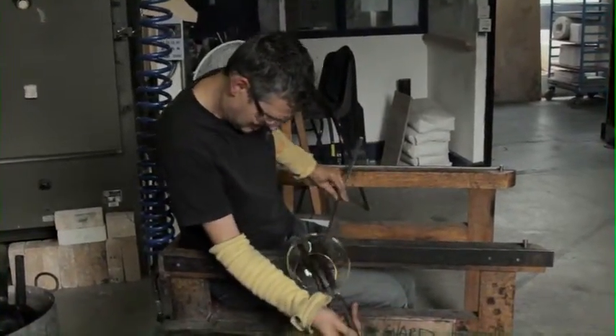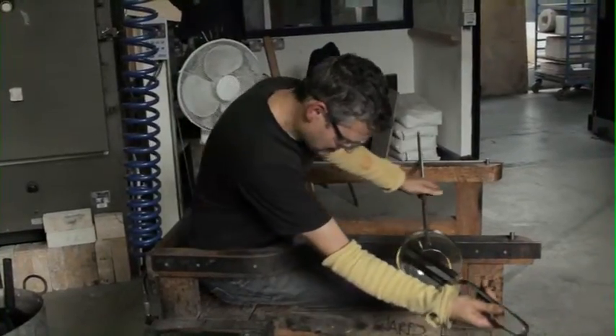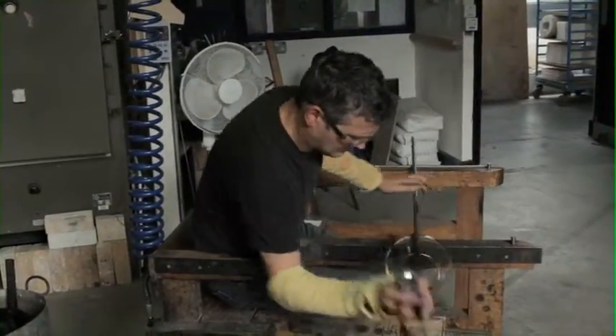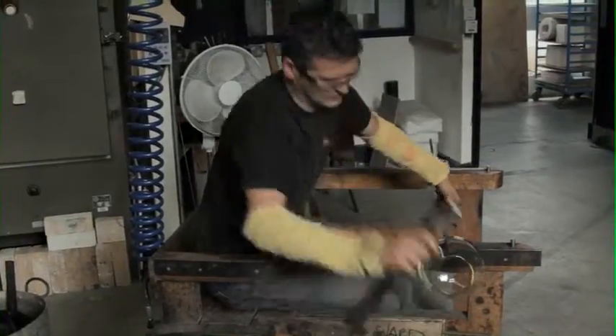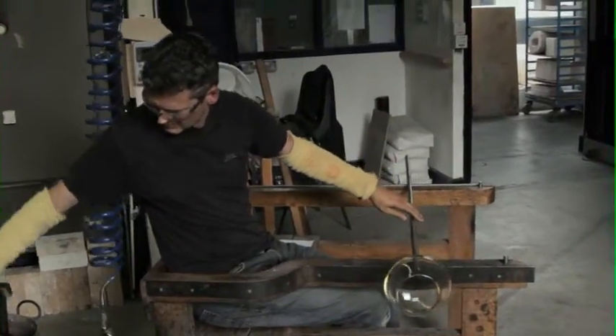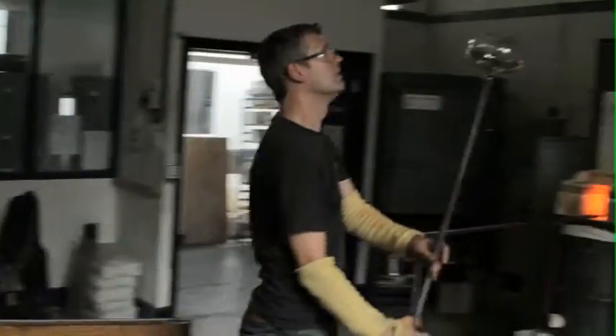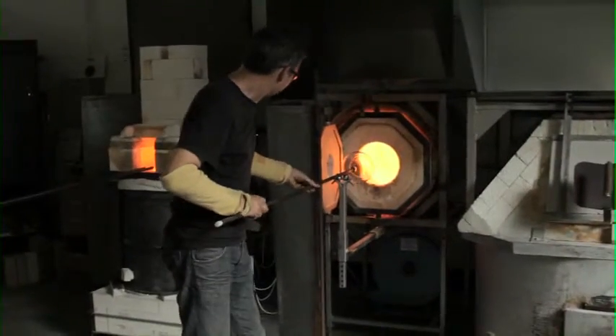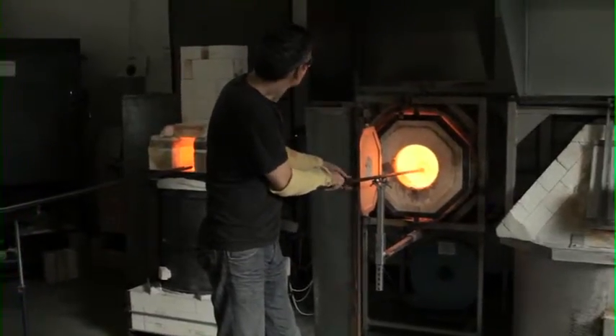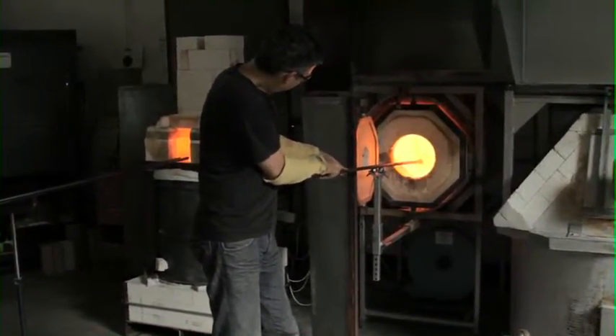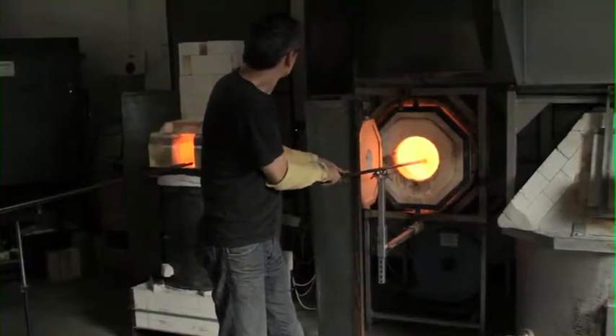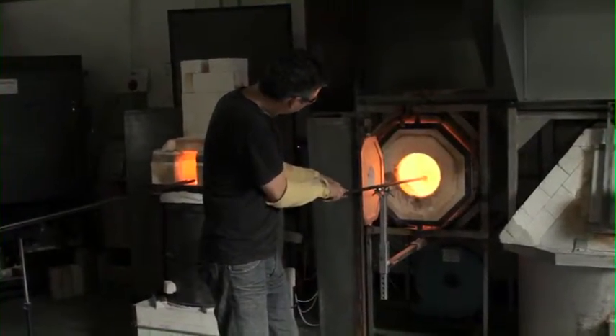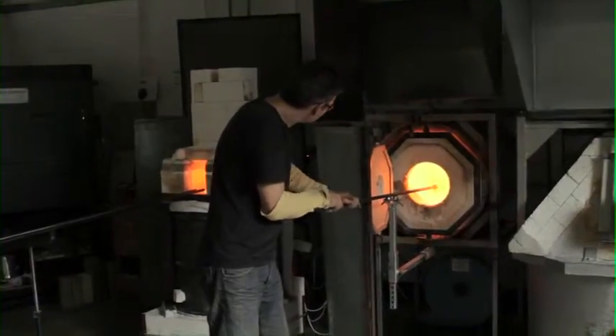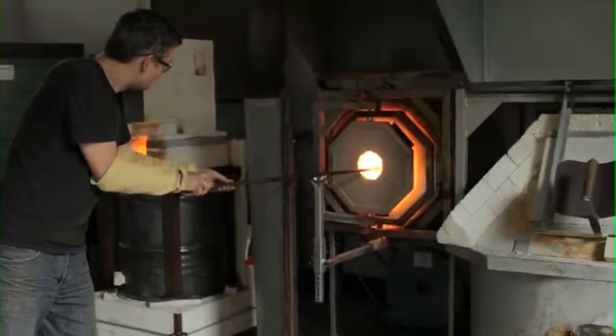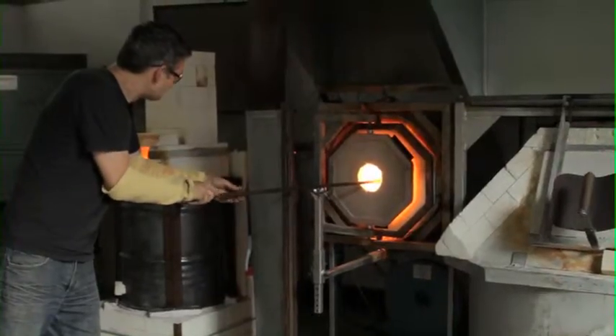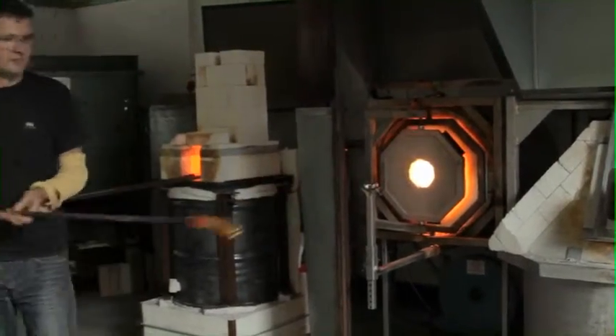I don't actually believe that the early glass makers had so much trouble with corrosive glass causing pot failure. Wide clay pots would ensure less contact with the walls, so the corrosive foam would be on the surface. Also, because the crucible was quite literally a pot made of clay, it would have to have been glazed with a little cullet poured on the inside of the crucible wall before it was filled with glass. This glaze provides protection from the corrosive foam. It's amazing to think that such ancient technology is far more resistant to corrosion than our most sophisticated refractory materials. So we were left in a position where we had to rethink.